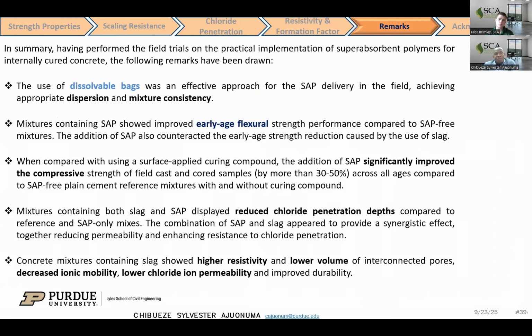So, in summary, having performed this field experiment, first of all, we're able to establish that the use of dissolvable bag was an effective approach to deliver SAP in the field, giving appropriate dispersion and mixture consistency. And then also we found out that the SAP improved the early flexural strength, as well as significantly improved the compressive strength performance of the concrete mixtures when we compare it with SAP-free mixtures, because we had values of between 30 to 50% strength increase compared to those without SAP.